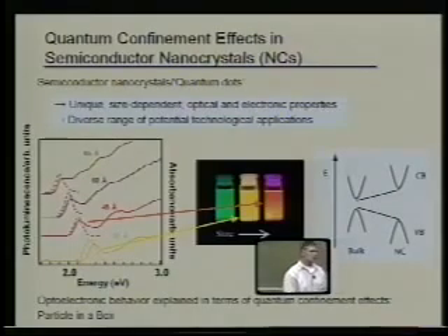So you say, okay, well, why do we need a synchrotron? Well, as it turns out, other nanocrystalline systems aren't necessarily characterized as well. And you find out that if you're just doing PL, and you don't know where it's coming from, you don't have any element specificity, you get really lost fast. So in some cases, the byproduct can have the PL, or the supernatant can have the PL, or the PL is coming from the surface, or it has nothing to do with quantum confinement. So when you have a very well characterized system, it's great, and there's been a lot of work done to prove what's going on in both the cadmium sulfide and the cadmium selenide. But if you're working on a research system, it is very dangerous just to go on PL by itself.